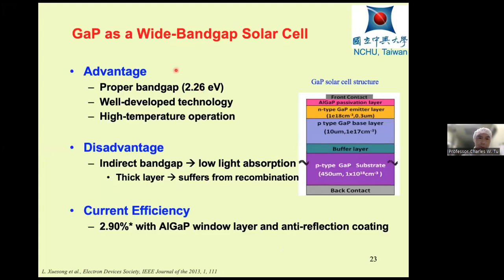Now I want to talk about the last application, which is solar cells. Gallium phosphide can be a wide bandgap solar cell because it has a proper energy, but because it is an indirect bandgap, it has lower light absorption, so we need a much thicker layer. The highest efficiency is like 2.9%, with aluminum gallium phosphide as a window layer and an anti-reflection coating.